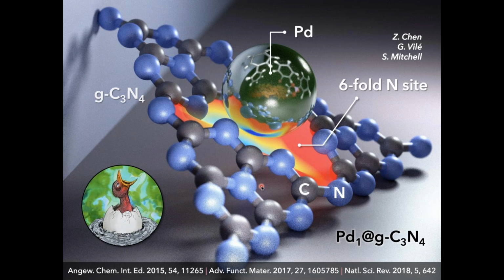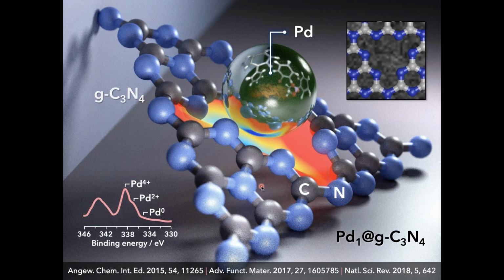In the picture that you see here is palladium. And by electronic donation between the nitrogen and the metal, this metal gets heavily stabilized in the structure. You can see that actually, if you look at this time resolved micrograph, where the single atom is mapped in the cavity of the nitrogen of the carbon nitride, and then you see the very important stability. Of course, if you see some movement, it is not because the atom is moving, it's because the grid of the microscope is moving. So this atom is really in place.